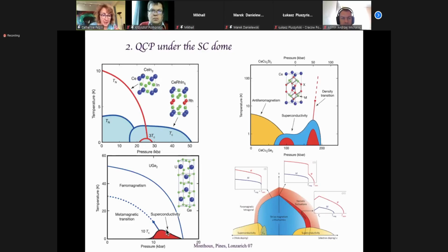They're usually D wave. They can be P wave, like in this case, where actually the magnetism is not antiferromagnetic, but ferromagnetic. And if you look at the pnictides, all the pnictide family have again antiferromagnetism and superconductivity in the dome. Here is this new heavy fermion with a valence transition here, density transition, superconductivity, antiferromagnetism. So this is not a very common thing, and it could very well be that, although it's not really antiferromagnetism, for cuprates we have another type of phase transition. Like here we see we could have a density transition, and superconductivity is generated by a fluctuation of the order parameter that will favor the pairing of the Cooper pairs.